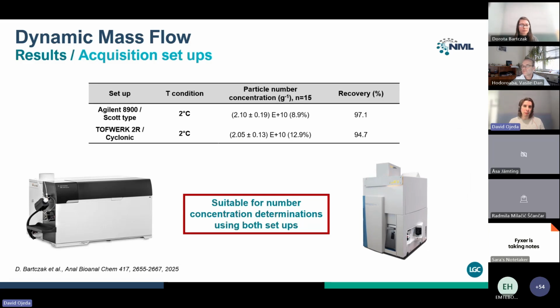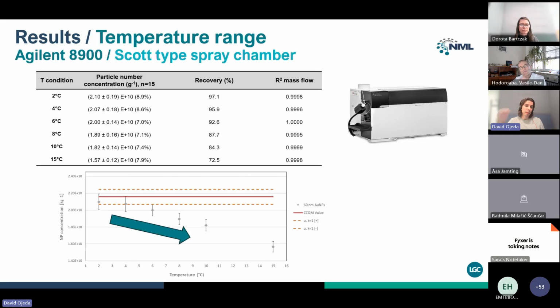First, we want to show the results for the acquisition setups with the original temperature conditions. As we can see in the table, the performance of the DMF was suitable for both instrumental setups with good recoveries in both cases. Then moving to the study of the temperature range with the Agilent 8900 with a Scott type spray chamber, we see there is a trend: as we increase the temperature of the spray chamber, the recoveries are dropping.